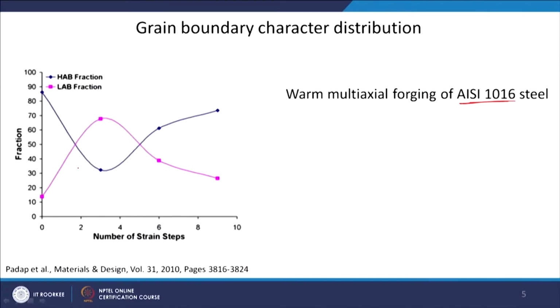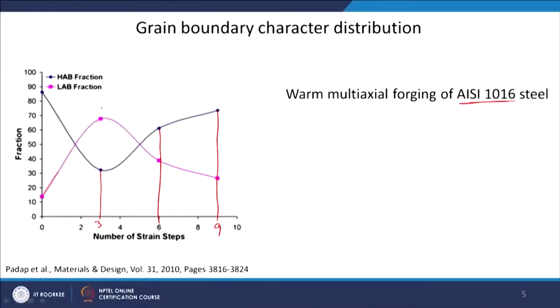So, obviously, if you see what is the effect of number of passes on the deformation. As I told you, in multi-axial forging we will be doing in multiples of 3. So, this is 3 pass, this is 6 and this is 9 pass. Initially the microstructure which was taken in this work was a well recrystallized annealed microstructure. So, the high angle grain boundary fraction was very high, around 85%, but as the deformation progresses, after the third pass, the high angle grain boundary fraction decreased from 85% to 30%. And obviously at the same time, because these fractions are calculated for the total, the low angle grain boundary fraction is increasing, going up to 70% after the third pass.